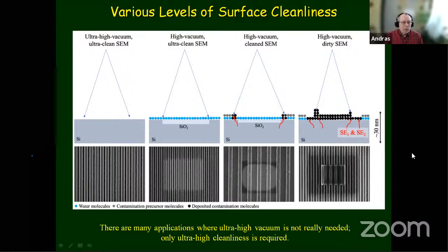We use a UV laser and an infrared laser to manage the surface during the measurement, during electron imaging, as much as possible. Obviously, you cannot do everything with that. So that actually showed some remarkable preliminary results. Later we'll publish a paper on that.